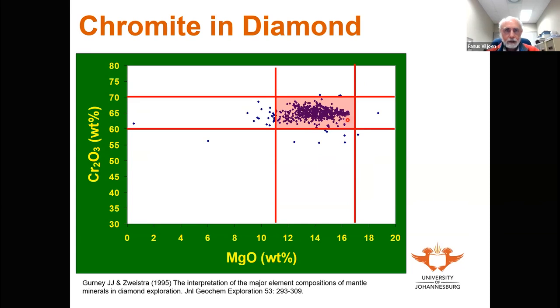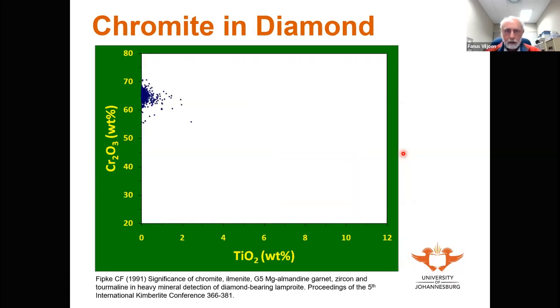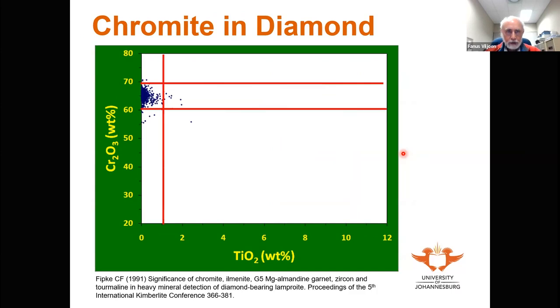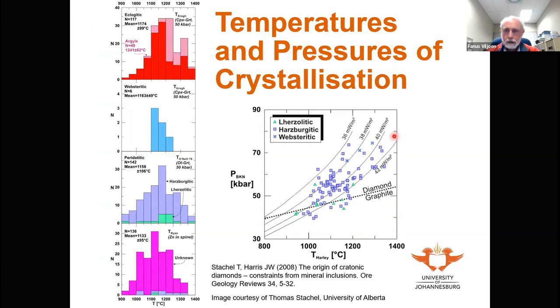But it's a lot more complicated than that, because you can see the same chemistry is also in chromites from the Bushveld complex, for example. There will be presentations dealing with this at a later stage. These same chromites occurring as inclusions in peridotitic diamonds also contain low titanium content. So again, if you see high chrome and high magnesium and low titanium in chromites in your prospecting program, that's potentially, with a little bit of complication involved in it all, from diamond-bearing kimberlite. And hence you may be able to sell that prospect on the stock exchange.